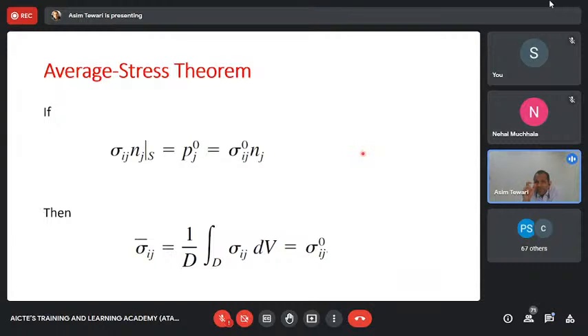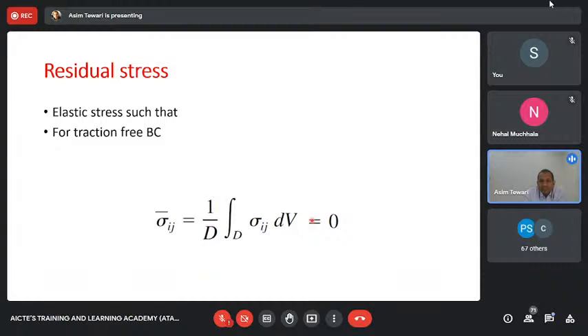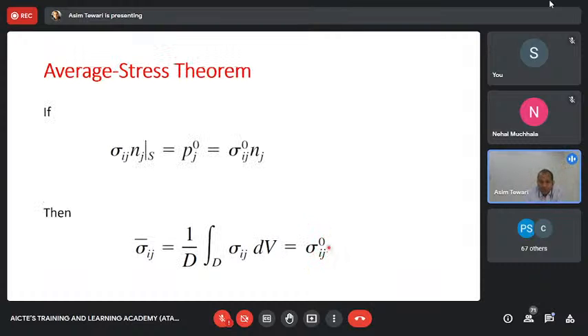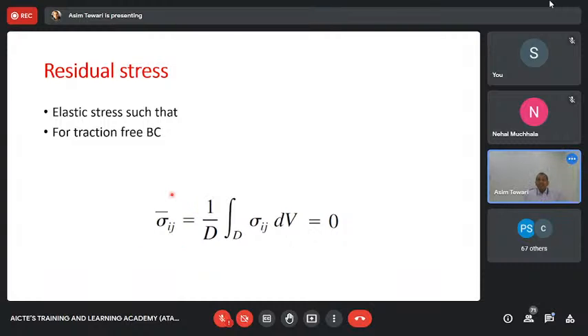Now what you need to realize is that if the sample is under a traction boundary condition given by this force, then the average internal stress of the body integrated over the entire volume is given by this quantity. Why am I talking about this? I'm talking about this because in a residual stress, there is no traction. It's a traction-free boundary condition. There are no external stresses. Since there are no external stresses, this stress is 0. And that's why the average residual stress in a body is exactly equal to 0. So that's the underlying reason why your average stresses are 0, which means that if you have a tensile stress somewhere, you will also have somewhere a compressive stress, so that the volumetric average of all those stresses becomes exactly 0. And that is one of the key aspects which you need to appreciate.